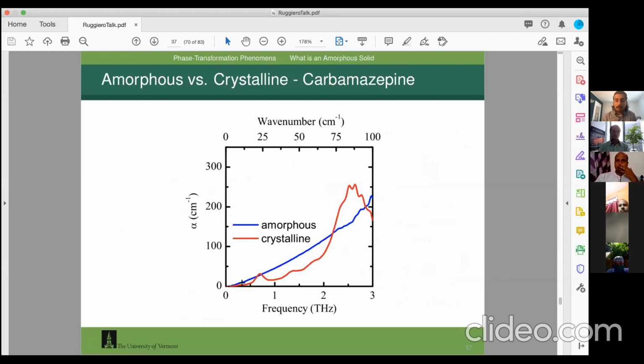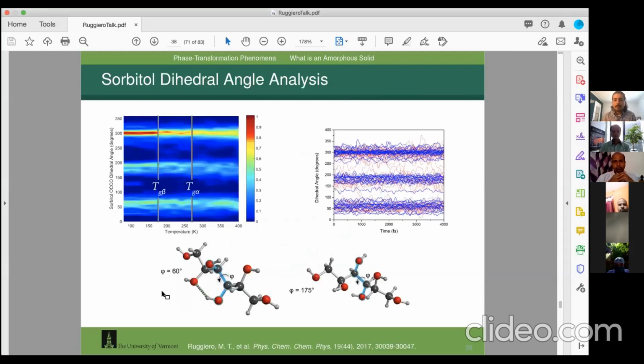If you look at these two schematics of a terahertz spectrum, the crystalline material has these nice peaks, a peak here, a peak here, a peak here. Whereas the amorphous material is featureless, just this broad featureless background. It turns out that broad featureless background actually has a lot of information in it that we can extract if we know what we're looking for.